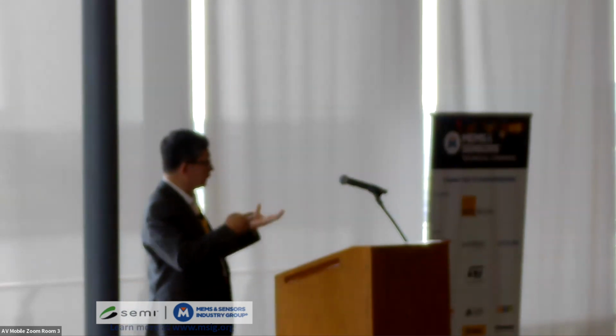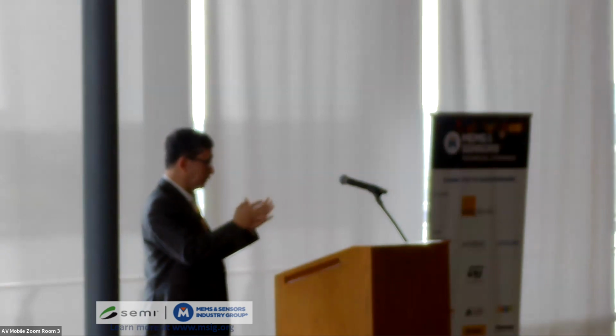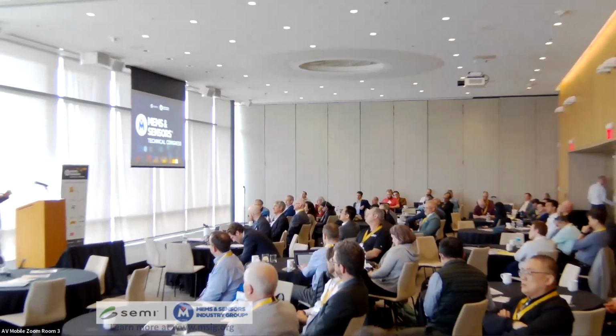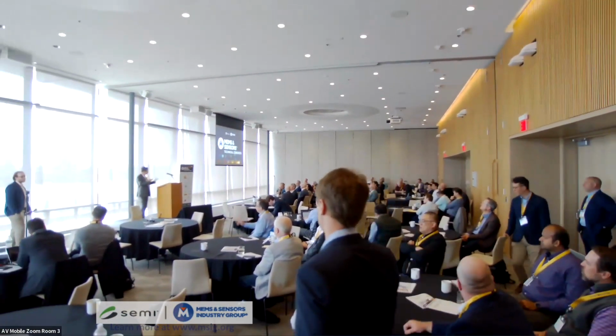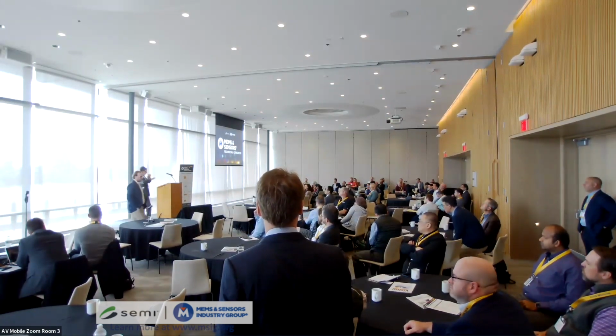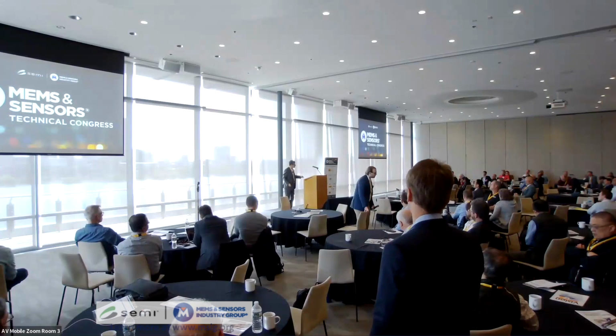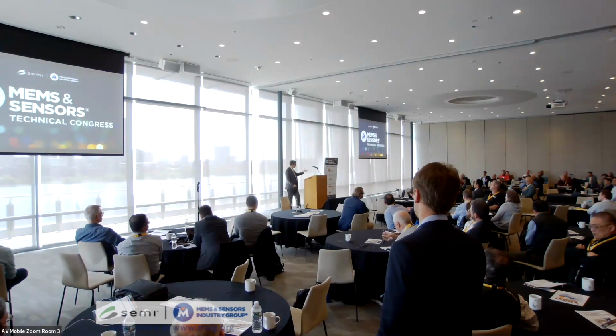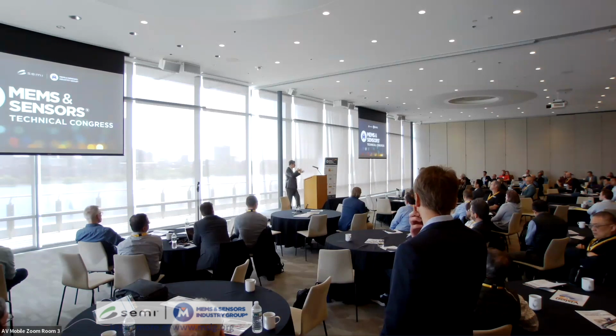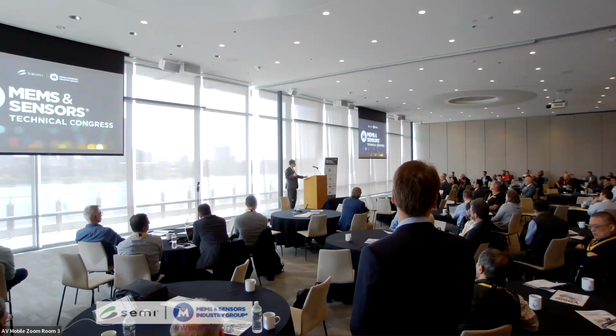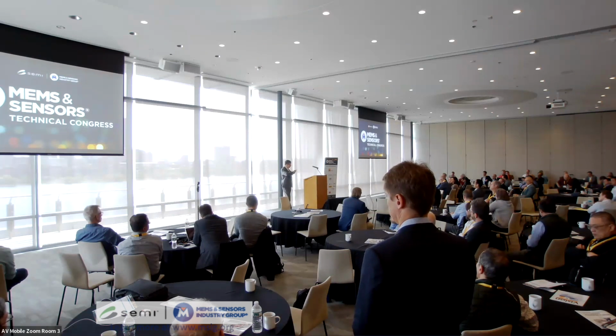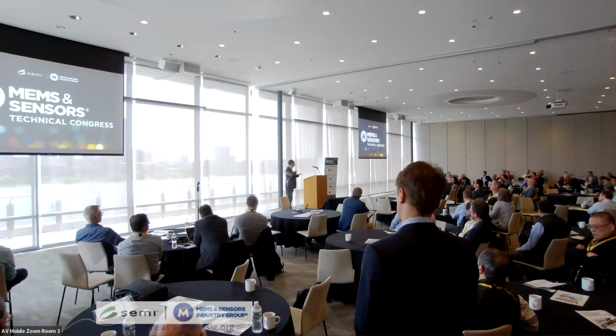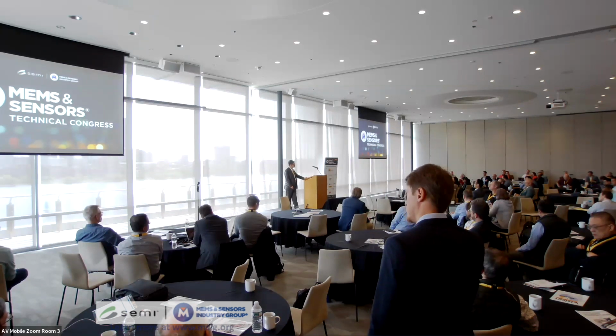The challenges are a lot of the equipment is looking for opaque materials, right? And the sensors sometimes use red light, sometimes use near infrared. So for glass to be handled in a conventional silicon fab, you really need to opacify the glass. So we have solutions putting either metal or some multi-layer coating to make it behave like silicon, so the silicon fab can handle it. And the second challenge is if it's a glass with aluminum or calcium, the front end typically doesn't like that. So we put a silicon nitride coating all around the wafer to make sure there's no metal on the surface. Thank you for the question.